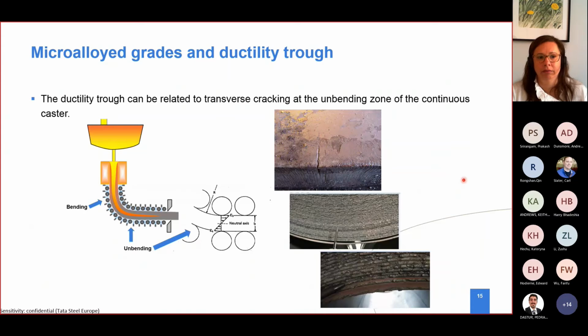But why are we interested in this? Well, if this precipitation happens, so if you have a ductility trough, it means that your steel is less ductile and it could even crack if it exceeds certain stresses during casting. That point is very important because it happens, depending on the precipitation of the steels, either at the bending or at the unbending of the continuous caster.